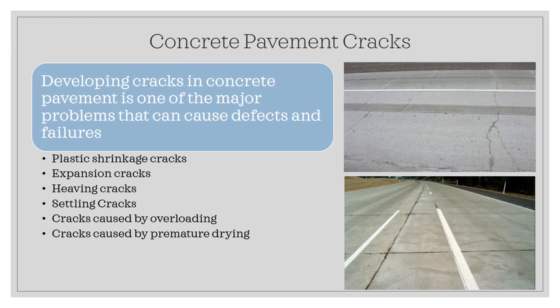While plastic shrinkage cracks can happen anywhere in a slab or wall or any different type of concrete structure, they almost always happen at reentrant corners or with a circular object in the middle of a slab. So wherever you have utilities or pipes and drainage, it's more prone to cracking there. Since the concrete cannot shrink around the corner, a stress will cause the concrete to crack from the point of that corner. The other type of cracks are expansion concrete cracks.